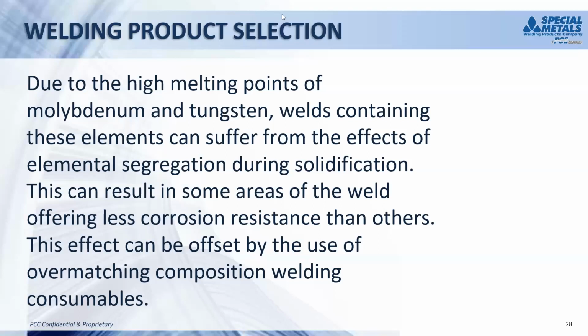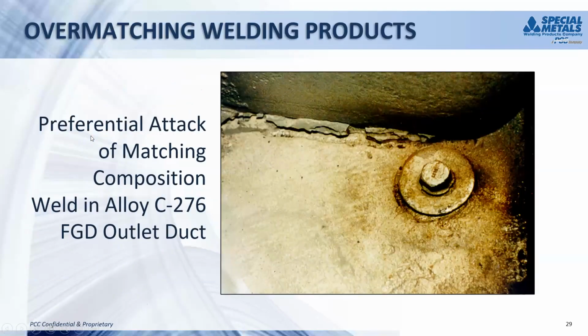The next slide shows what can happen if you don't use an overmatching composition weld. This is that same duct that I showed you earlier where we exposed the 4-sample test. This is alloy C276, and you can see the weld is just almost corroded away. This was welded with a matching composition filler metal, and the weld has just basically lost all of its structural integrity.